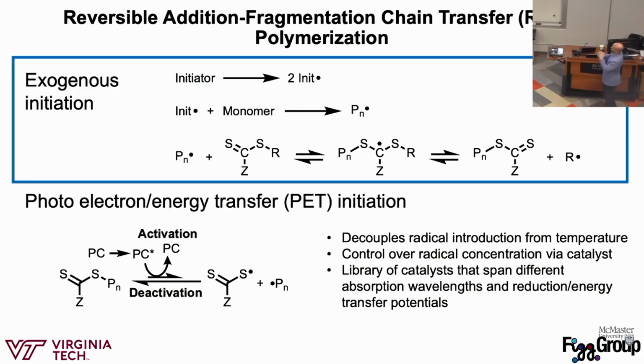What we do is we get some sort of photocatalyst that we can excite with light. The excited photocatalyst can undergo either an electron or an energy transfer reaction with the thiocarbonyl thio. In this case, I'm showing an energy transfer because we end with two radicals. So after this energy transfer, we initiate, and this can propagate, and then you'll get a deactivation step where these radicals just recombine to give you your starting RAFT agent.